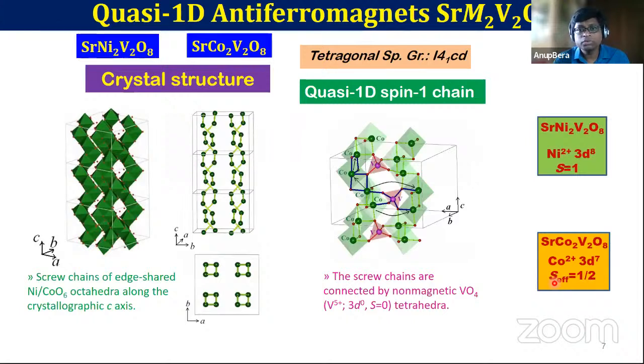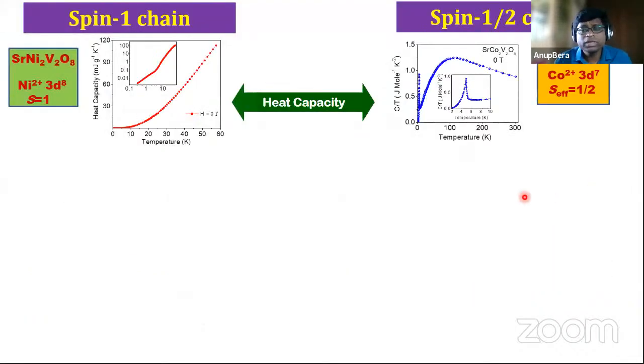So the compound I'll show has a one-dimensional chain-like crystal structure where the cobalt octahedra share edges and form a chain. In this case it is not really straight, but it shows a screw type of chain, but it is approximately linear. And the chains are well separated by the VO4 tetrahedra. Vanadium is in the 5+ state, so it is d0, so it doesn't carry any spin. So in my system, it is spin cobalt 2+. There are 7 electrons in the d shell, but I'll show that it effectively becomes spin half. And a quick comparison will be given with the nickel compound, which has 8 electrons in the d shell and carries spin 1.